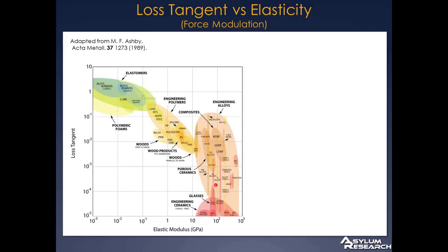As we go up in the metals, the loss tangent increases, so you increase the damping without reducing the stiffness too much. But you'll see that, for the example of a lead alloy, a lead alloy with a loss tangent of 10 to the minus 2 doesn't make a very nice bell. Sort of makes more of a thunk or a thud.